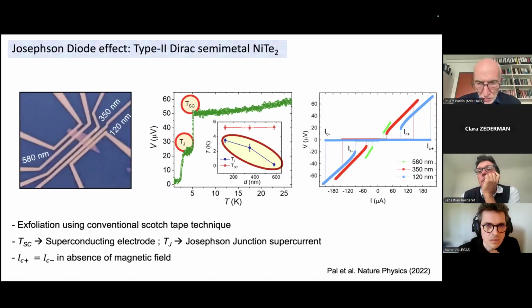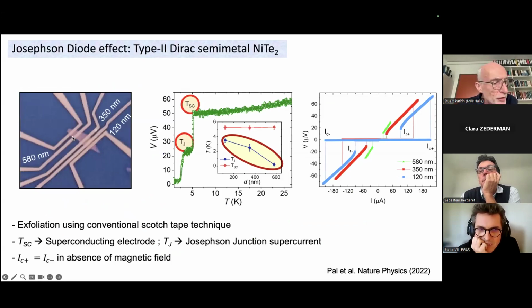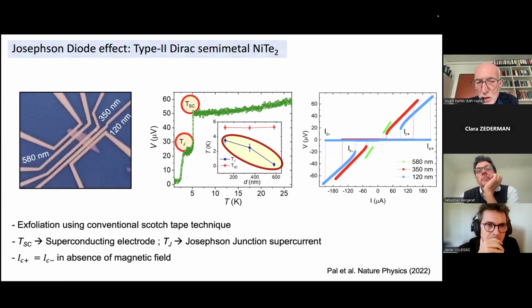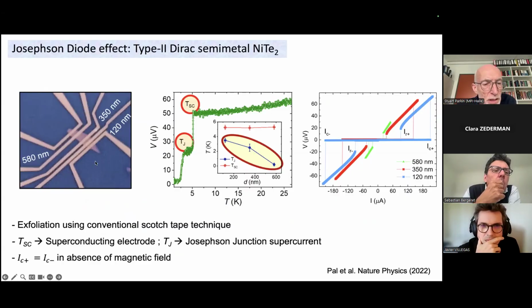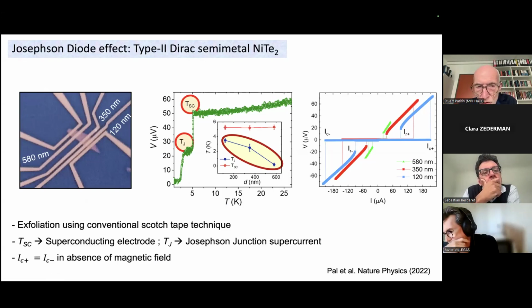So this is our basic results. What we do on the left-hand side, you can see we take a flake of this van der Waals system, a few microns wide, and then we build on top using standard electron beam lithography techniques. We build niobium contacts. You can see these contacts in the left-hand side, and the niobium wires are separated by, you can see the spacing is 120 nanometers, 350, and 580 nanometers. This is the concept. So on one flake, we can build lateral Josephson junctions, where the spacing between the electrodes is varied. Otherwise, we know that the flake is identical for all of these.